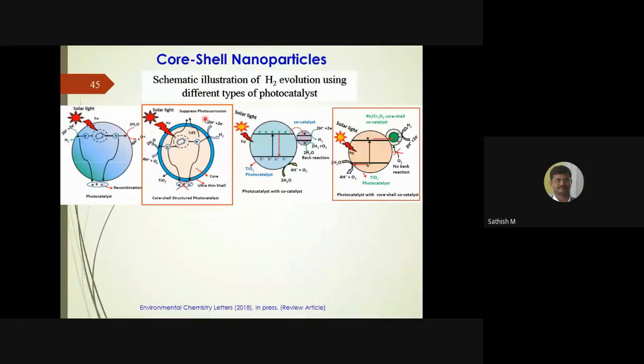So the light can penetrate through this, and then this excites the cadmium sulfide. Now, visible light can be used to excite this cadmium sulfide, but this cadmium sulfide is not exposed to the electrolyte, or the solution. So because of this, the photo corrosion could be avoided.